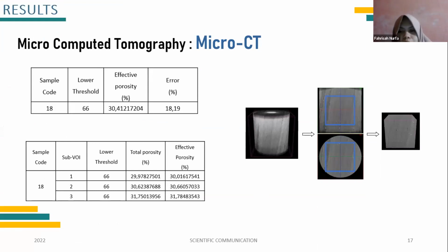analysis was also carried out to determine the effective porosity value of the sample. The software used is called CT Analyzer. In the sample image, the VOI or volume of interest is cut because there are parts with non-uniform contrast, such as in the top and bottom areas of the sample image, as you can see in the illustration of VOI cutting in this slide. And the sample image is cut into blue blocks in the illustration.